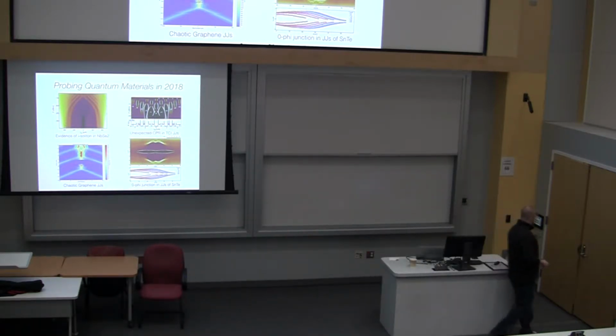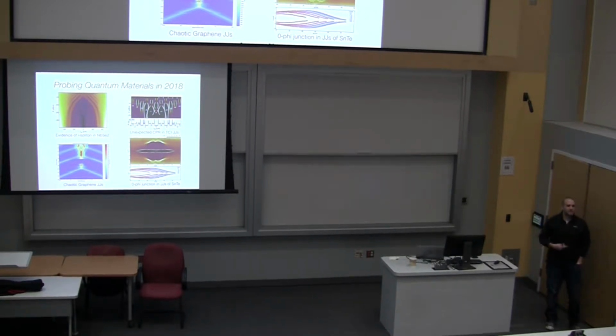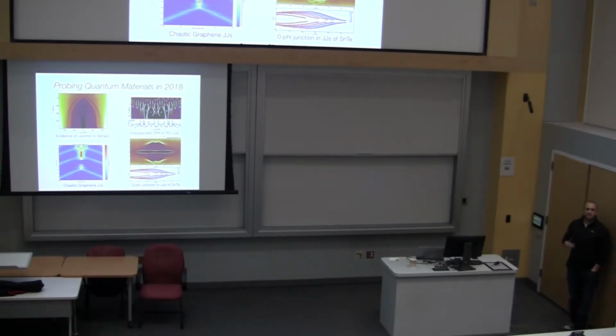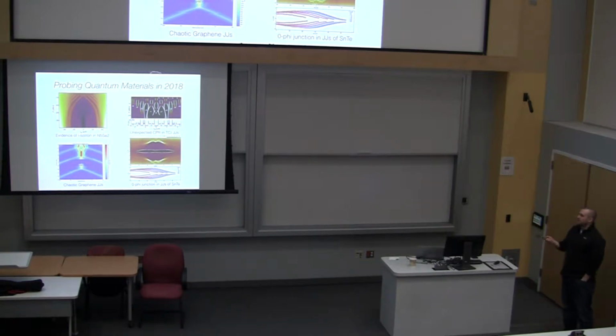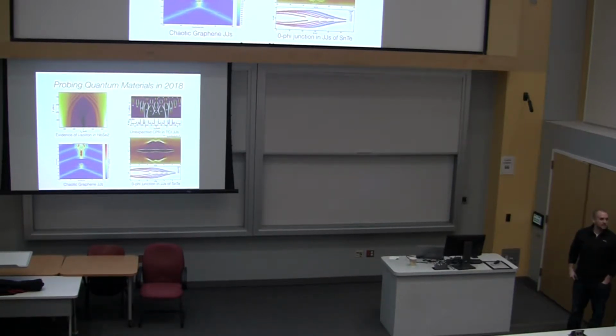Something that JP knows about a little bit is that in niobium diselenide, there are two bands. Niobium diselenide is a superconductor, and the question really is, how does a superconductor relate to each other in these two bands? And if there's weak coupling between these two bands of superconductivity, some very interesting phenomena can happen with Josephson junction-like physics between these two bands.